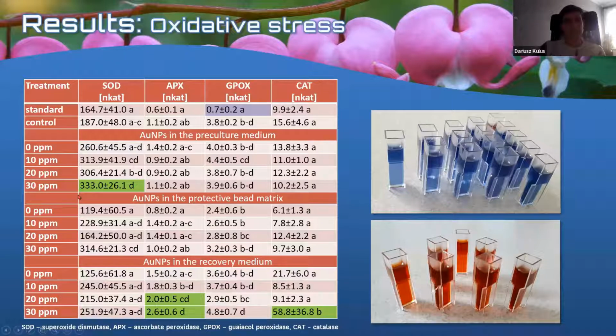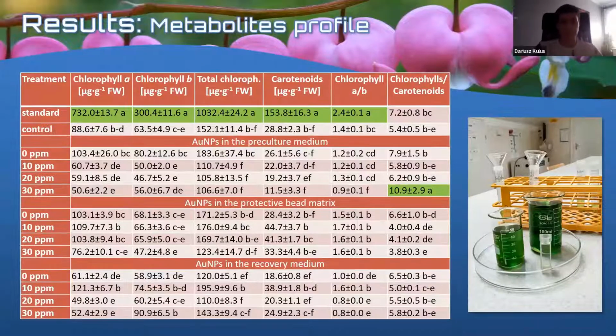As you can see, the addition of higher concentrations of nanoparticles into the pre-culture medium or to the recovery medium increased the activity of those enzymes. However, when the nanoparticles were added to the protective alginate capsule, there was no significant increase in the activity of enzymes. So there was no additional oxidative stress put on those plant tissues, which is important because, like I said earlier, this combination allowed us also to increase the survival rate of the plant material.